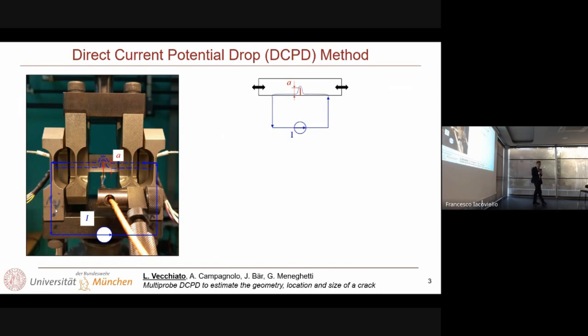It is that we have a specimen which has a crack inside, which is loaded with the fatigue loadings, and the potential drop consists of injecting a constant current through the specimens. And since the crack is propagating during the test, the ligament section is reduced, and somehow the electrical resistance of the specimen is increased.